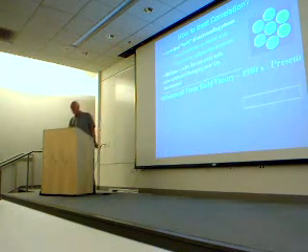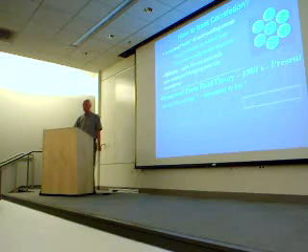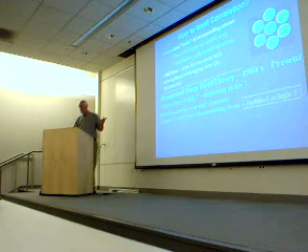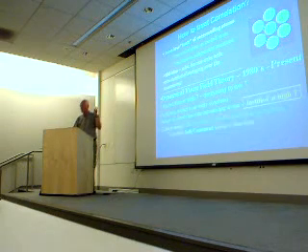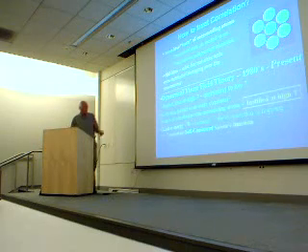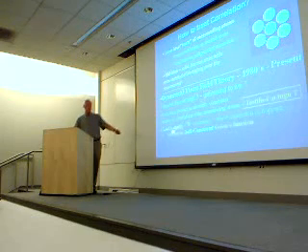So dynamical mean field theory comes along, and it uses the same idea, but it really puts in temperature. Each atom is strongly correlated, and at first it neglects correlation with the surrounding atoms, which is valid at high temperatures. So you still have this reduction of kinetic energy, and then you go ahead and try to put in the correlation with the surrounding atoms.